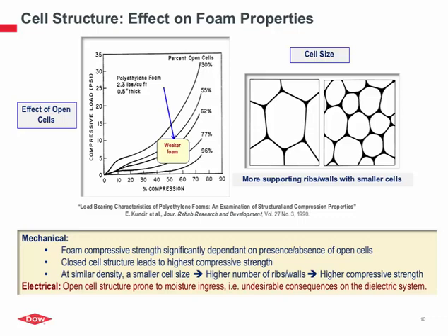From an electrical standpoint, which we should not forget, an open cell structure is prone to moisture ingress. That means undesirable consequences. Of course, moisture is not a dielectric medium, so that would affect the dielectric properties. Also, the manufacturing lines for these telecom cables do have an inline spark fault detection, and the spark fault can apply up to 12 kV continuously at frequencies as high as 2.5 kilohertz. So there is continuous monitoring of the insulation integrity as the cable is being made. If we have a weakness in the dielectric medium or layer, for whatever reason, contamination, moisture, or breakdown in the dielectric path, that would all result in a spark fault, and of course the cable is not usable.